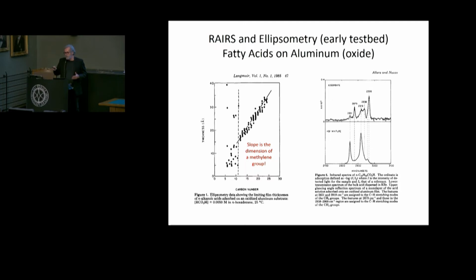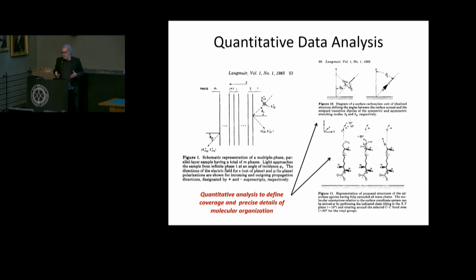You can characterize those optical anisotropies shown in the experimental spectrum in terms of a theoretical spectrum for that mass coverage of material at an isotropic distribution relative to the underlying substrate. What it would look like, and compare that to what it actually looks like, and from intensities and band positions, and actually measuring intensities quantitatively, come up with a structure. Okay, and that's what was done.